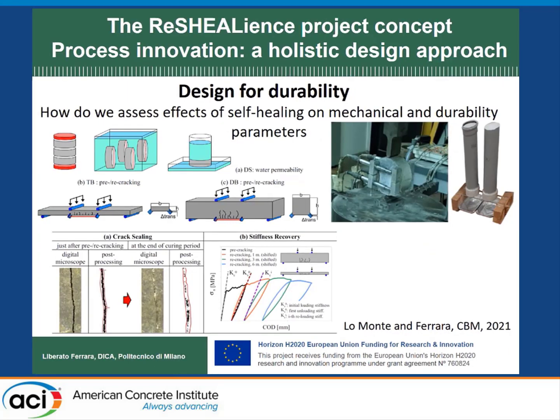So we performed an extensive experimental campaign. You can see the evidence of crack healing. We also evaluated the recovery in water permeability. You see this homemade setup that we built and used during the lockdown, when access to the lab was not fully available. So we had to make do with homemade equipment.